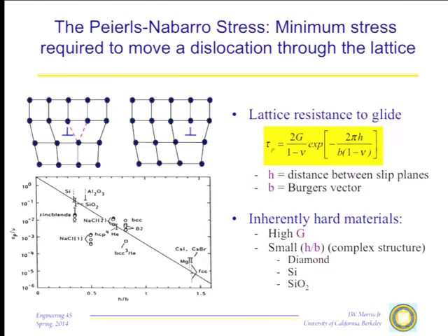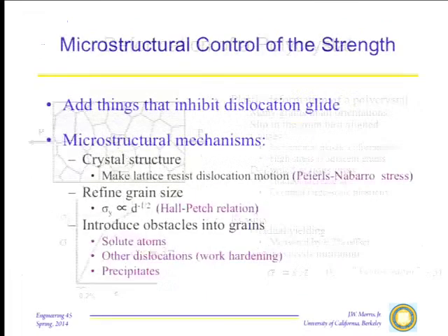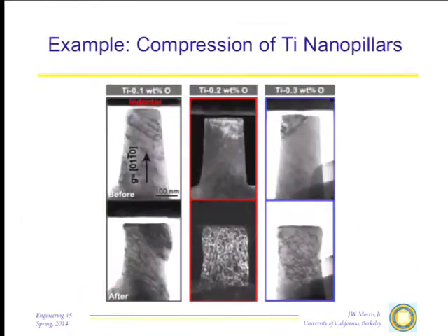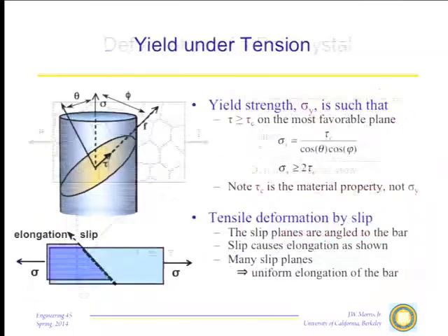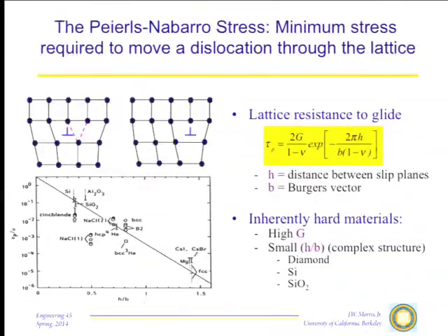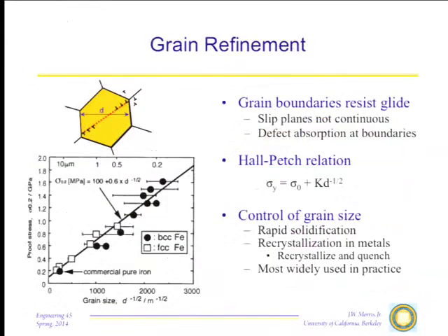One of the ways you can tell whether the Peierls stress is high or not, if you have a material with a high Peierls stress and you image the dislocations, they will tend to be very straight because it's very difficult for the dislocation to wiggle from one plane to another. In materials that have lower Peierls stresses and are more ductile and more easily deformed, the dislocations are quite irregular, they're curved, they essentially are all messed up, kind of like you saw in the titanium example back here. You see these dislocations are very general in their shapes, and that's indicating the relatively low value of the Peierls stress in the material. If that were quartz instead or alumina or something like that, you'd see almost dead straight dislocations in the material. Very hard to move.